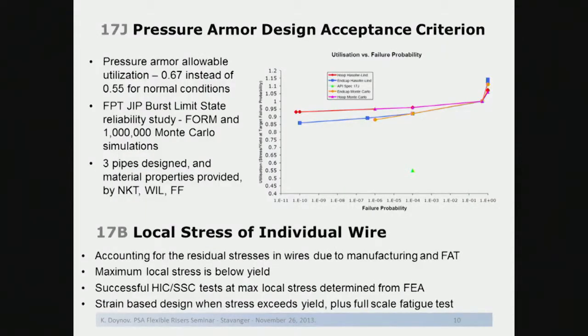And what you see with the solid lines is the result from the reliability study, and the upper lines represent the failure probability versus stress utilization for the hoop strength layer, while the lower lines represent the failure probability versus stress utilization for the tensile layers due to the end cap effect. So it's sufficient to say that there is plenty of margin existing in the way the manufacturers currently design those pipes. So that's the basis on which we relax the criterion from 55% to make it equal to 67%, which is the same for the tensile layers.